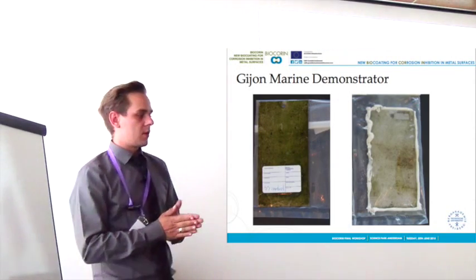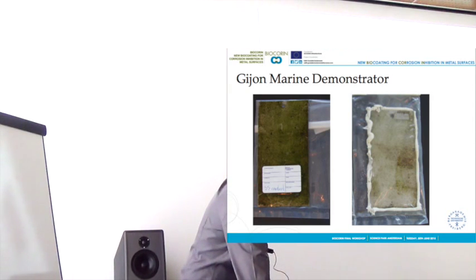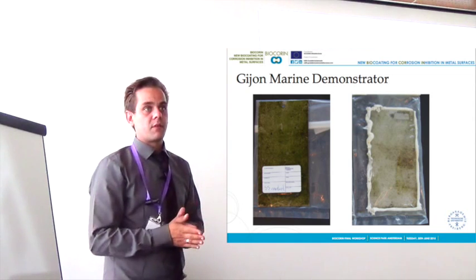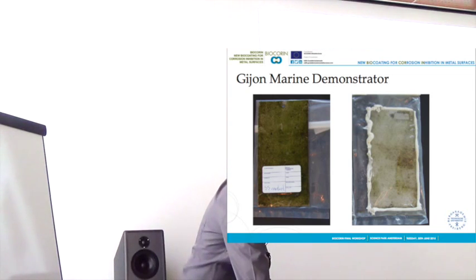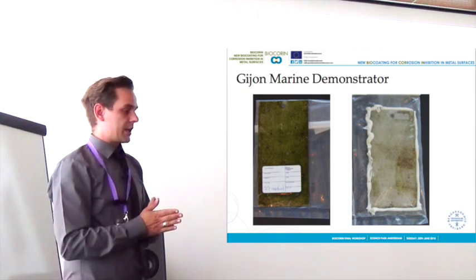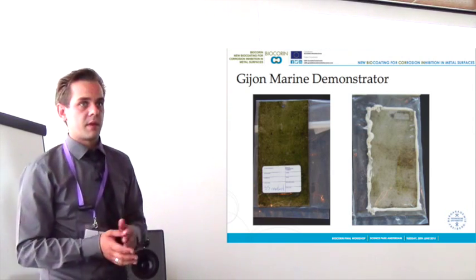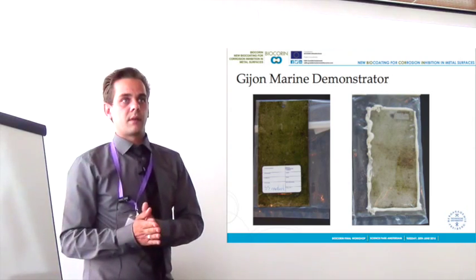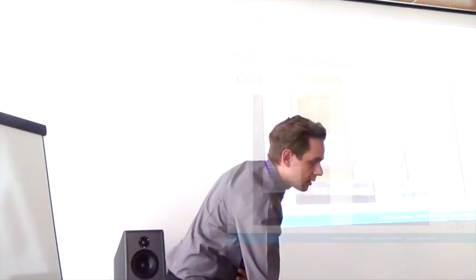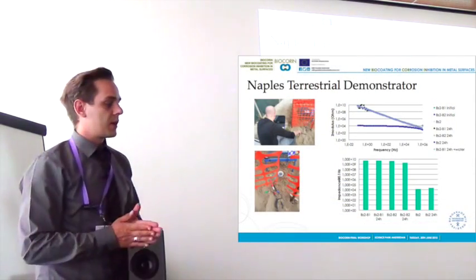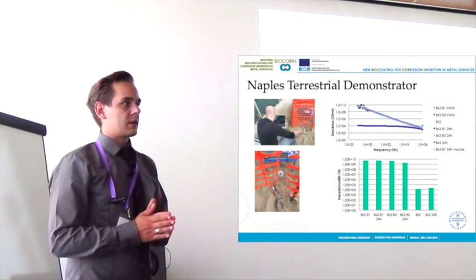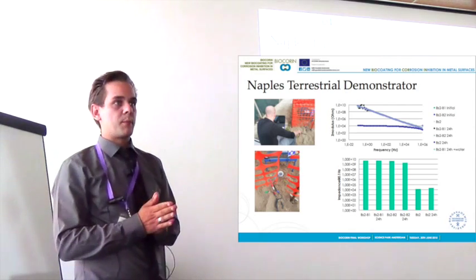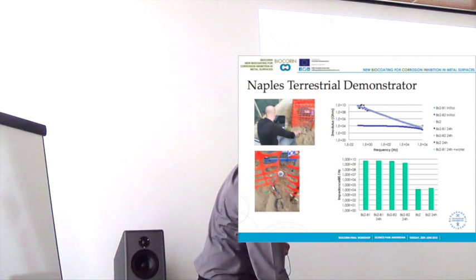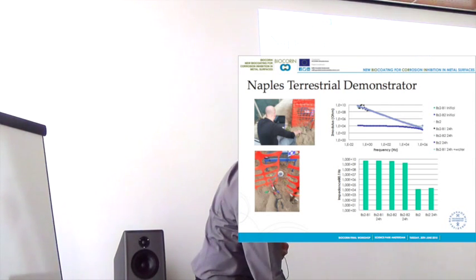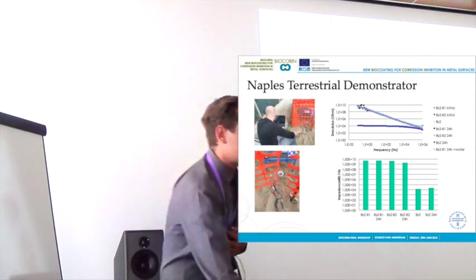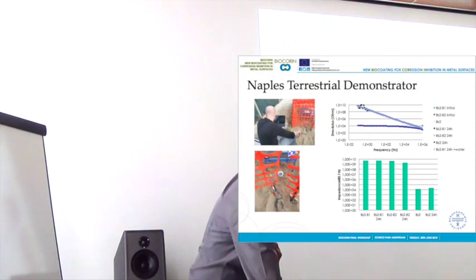Here we have first results from the Gijón marine demonstrator. On the left side, you have a control plate. Here you can see that a lot of green stuff is attaching to the surface and it's growing. On the right side, we have a steel panel coated with B2 and the integrated microorganisms. As you can see, there's still something growing, but the growth rate is dramatically decreased. Here we have first results from the Naples terrestrial demonstrator. VLCI had attached a device to check all the time the corrosion resistance of the coating, and B1 and B2 are the new formulations, and as you can see, they are working really well in contrast to the old one.